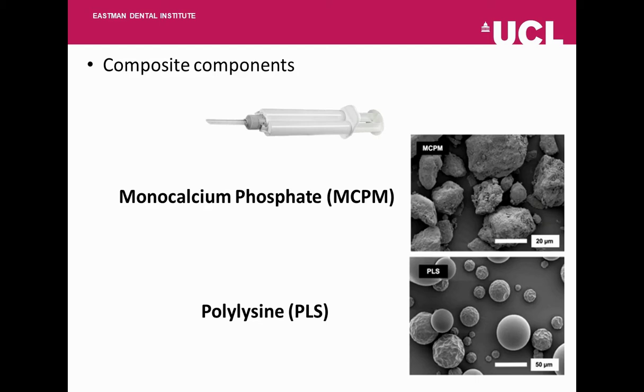Also, what's important about our composite, one of the components, is that it consists of monocalcium phosphate. These allow remineralisation, which means the composite will release components that in chemistry are very similar to bone, and this will allow integration with bone. We've also added polylysine. It's a very common antibacterial agent in food products, and we're hoping that this will work as opposed to antibiotics, because there's a lot of resistance to antibiotics at the moment, whereas with polylysine this has not been seen.